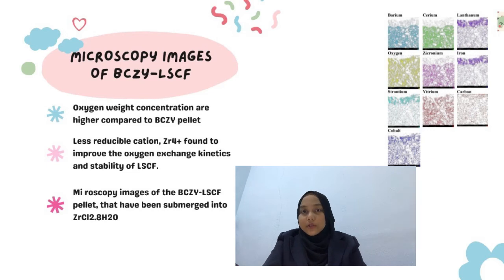In the methodology, it is mentioned that the pellet is submerged in ZrOCl2 8H2O at the temperature of 80 degrees Celsius. This is because it is needed to ensure that the excess strontium is removed and the surface is modified with metal cations. Also, it is done to ensure that the surface exchange kinetic does not degrade to a very huge extent compared to the initial surface oxygen exchange.